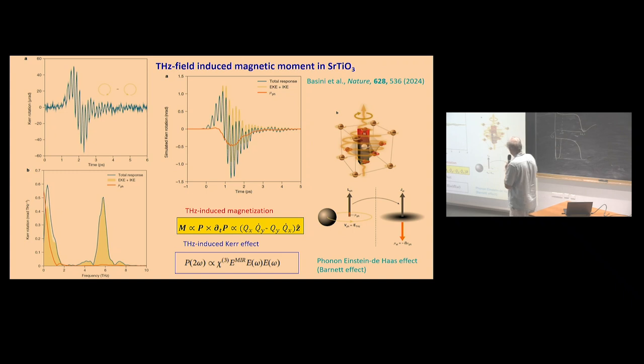But when she calculated the magnetic induction due to movement of atoms, she decomposed this effect into the magnetization effect and also the electron and ionic Kerr effect, which are these oscillations. These oscillations are responsible for this peak and also this second peak due to optical rectification, and the magnetization should be this red curve at 0 frequency.